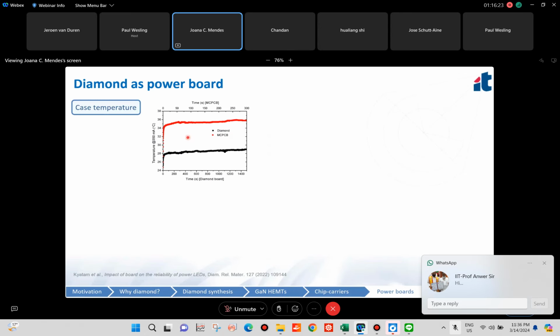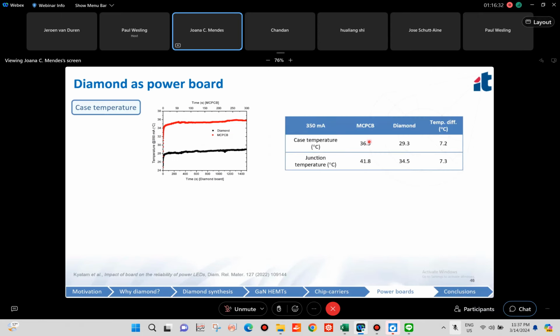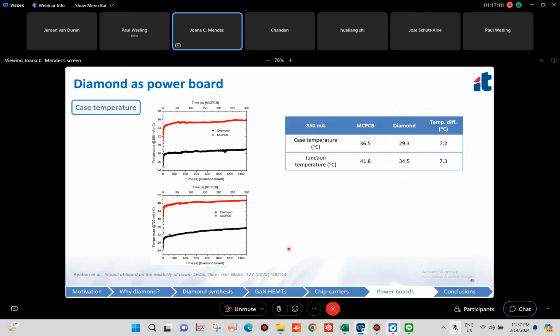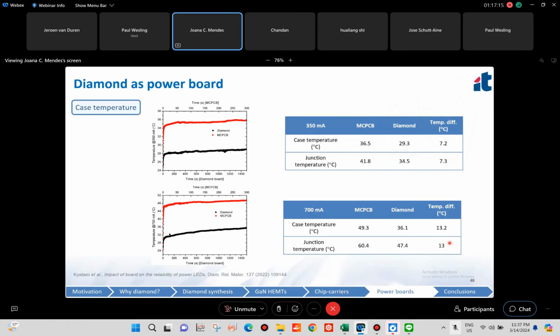So here we have nominal current. You see that the temperature of the MCPCB was slowly increasing until it reached a steady state value of around 36.5 degrees C. And when we had a diamond board, we could see that the steady state temperature value would be 29.3 degrees C. And this gives us a temperature difference of 7.2 degrees C. From here, we estimated the junction temperature, taking the values provided by the manufacturer, and we estimated a 7 degrees difference in the junction temperature by replacing the MCPCB with diamond. And then we've done some measurements at 700 milliamps, and of course the difference is more prominent. So we had 13.2 degrees difference in the case temperature, which translated roughly into 13 degrees difference in the junction temperature.